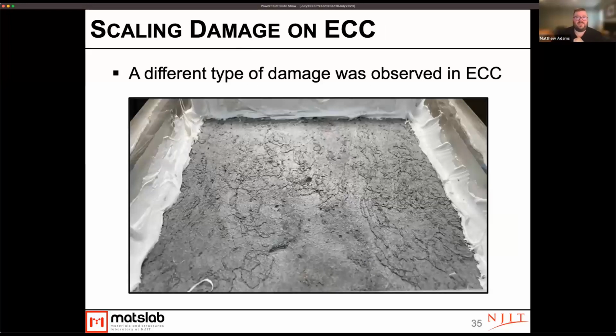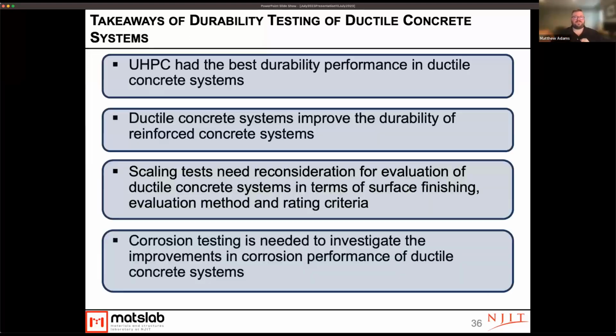And then on the ECC system, we actually noticed a slightly different type of damage. Instead of small pocks, we got sort of larger delaminations. And this is likely due to the density of the fibers that are in that system, sort of holding those surface pieces together. And so you get thin delaminations across a larger area rather than small individual pocks coming off. So takeaways of our durability testing, really UHPC across the board for the durability testing had the best performance. In general, the ductile concrete systems had improved durability, though the high FRC was a little bit questionable.